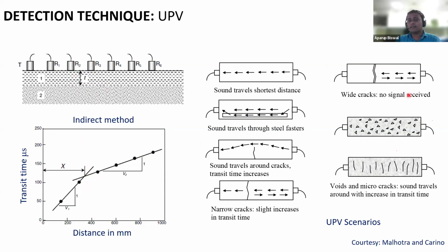And here you are seeing multiple cases. In this case, there is no transmission of the wave, but dip this in water or go to an area where moisture is high, and you will see that this will start showing values. Please remember that's a wrong value. You should not have done that test in a highly moist condition where a path is there for the wave to pass through to the next. You will report some higher values. You may report that quality is bad, but this is the true condition which is supposed to happen.